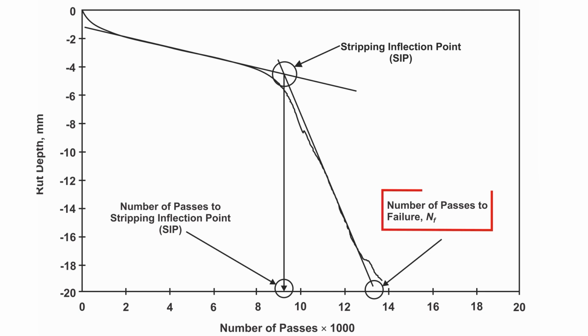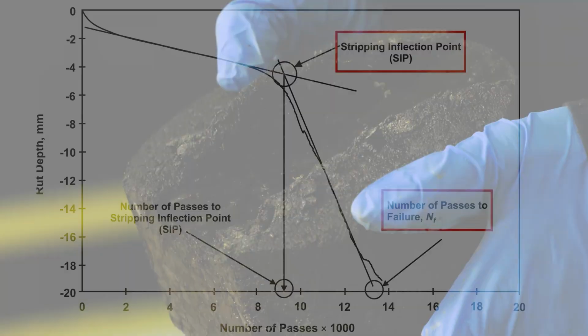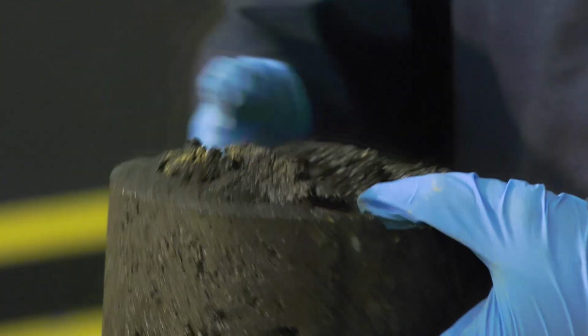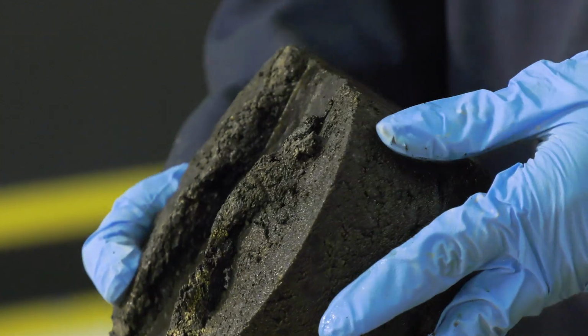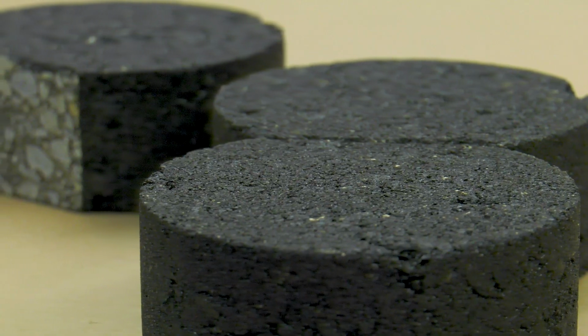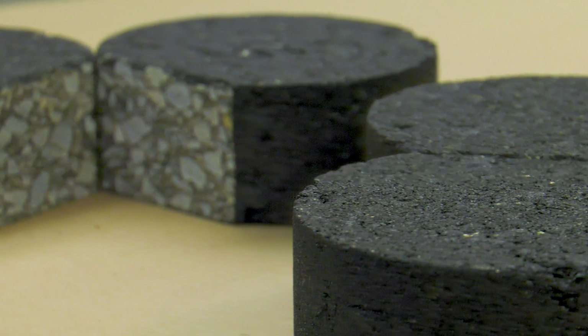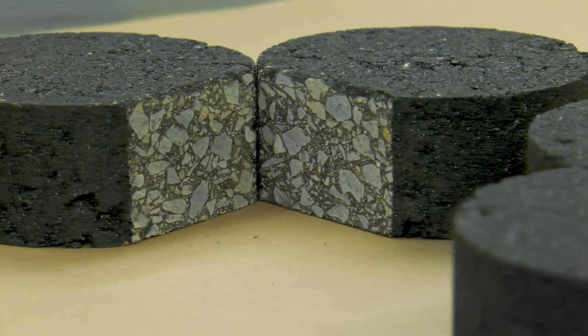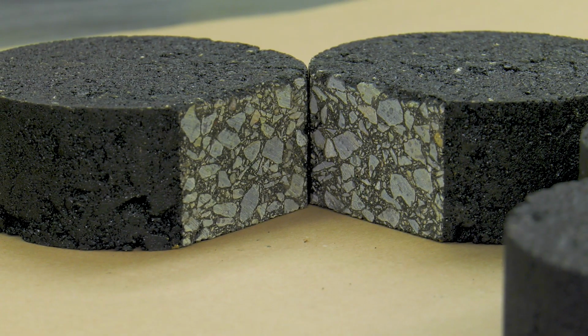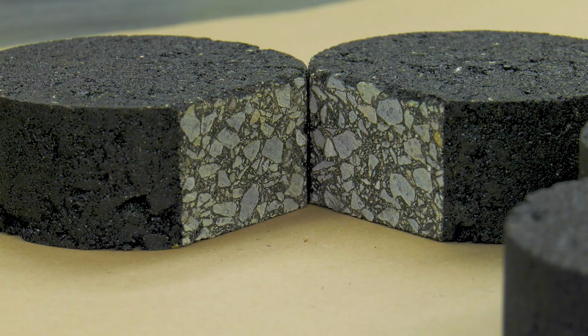Analyze the test data for number of passes to failure and stripping inflection points as described in the standard or methods specified by the agency. The rut depth can be taken as an average value of the 5 middle deformation locations. For a typical Hamburg Wheel track test result report, 2 sets or pairs of SGC specimens are tested, using a total of 4 SGC specimens.